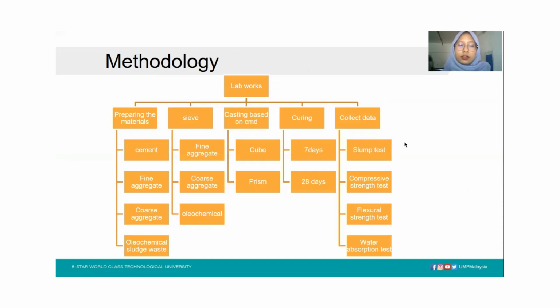The lab works include preparing the materials, which use cement, fine aggregate, coarse aggregate, and oleochemical sludge waste. For the sieve material, we will see the fine aggregate, coarse aggregate, and oleochemical. After that, we cast based on this mix design in the form of cube and prism. For curing, there will be 7 days and 28 days, and collect the data for slump test, compressive strength test, flexural strength test, and water absorption test.